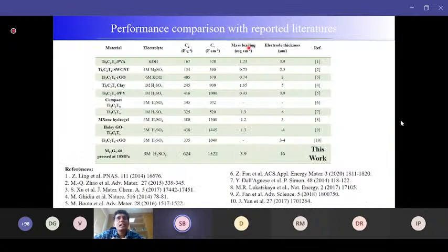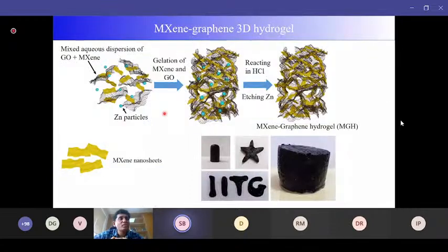And here is a comparison chart which shows that our performance, like this volumetric performance, 1522 farad per centimeter cubed, is much higher than most of the previous reports. And not only this 2D hydrogel which I introduced, we have also done a 3D hydrogel, where instead of a zinc plate, we use some zinc powder and let them gel in the form of a 3D hydrogel, and we succeeded in making the 3D hydrogel and some casting in different forms. So it shows the versatility of making the hydrogel according to any customization.